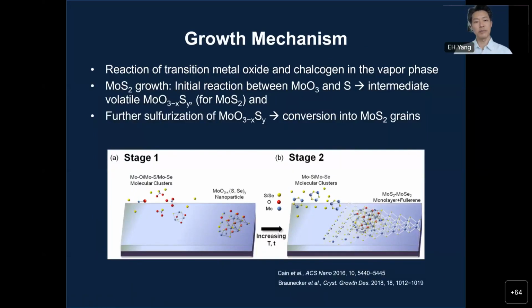It is based on the reaction of transition metal oxide and chalcogen in the vapor phase. For example, for molybdenum disulfide growth, there's an initial reaction between molybdenum trioxide and sulfur. In our case, this molybdenum trioxide is in thin film form, right? But conventionally, researchers use powders. Then it creates an intermediate volatile suboxide, which is further sulfurized. Then these materials are converted into these molybdenum disulfide grains.